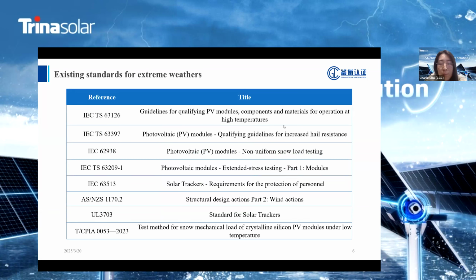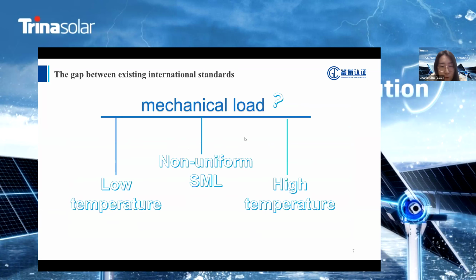To tackle this extreme weather, several standards have been published to evaluate the module performance. Besides our type approval standards and international standards like IEC standards, there are only 2 subjected to typical extreme weather. One is 63397 for large hail, and another one is 62938 for heavy snow. So there are still some gaps between existing international standards, especially referring to mechanical load. The type approval test could not fully represent the real cases of strong winds. So the IEC committee is discussing to supplement more tests to mechanical loads like low or high temperature mechanical loads or non-uniform static mechanical loads.